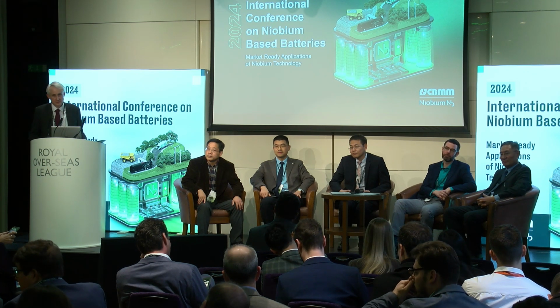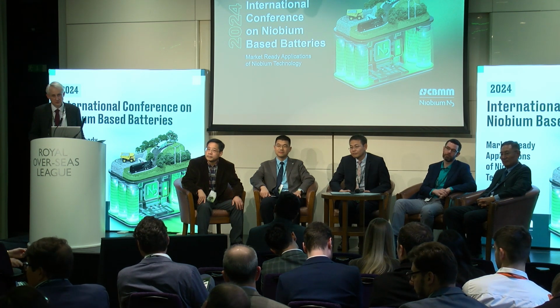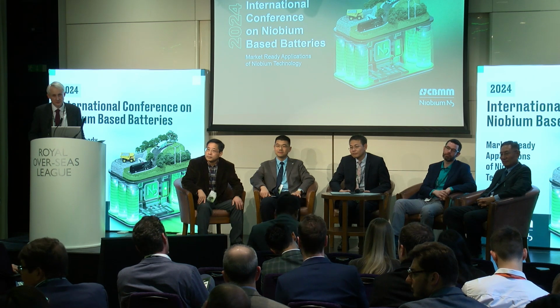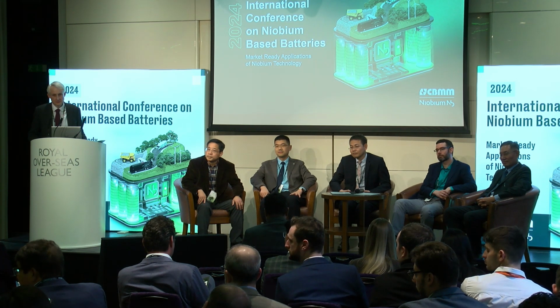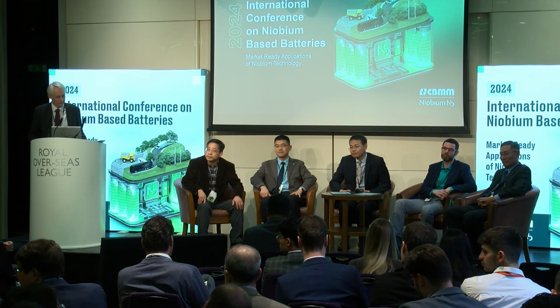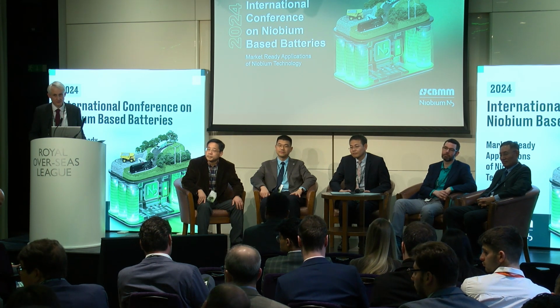It's not surprising what Mark said about the coating, that the micro size is better coating because maybe you can have a lower amount, is a better coverage of the surface, depends on the way that you prepare. There is some trends also, people working on amorphous phase of niobium oxides with high surface area, depends on the process, and also can have very good coatings in the materials itself. For nano sizing, I think the learnings that we are having is a good for doping.